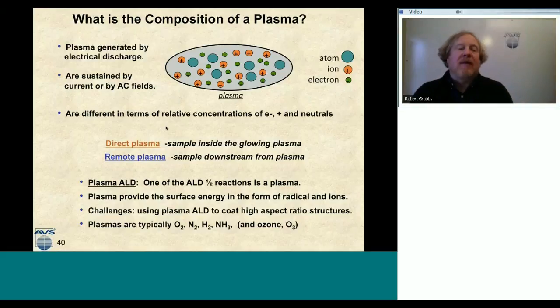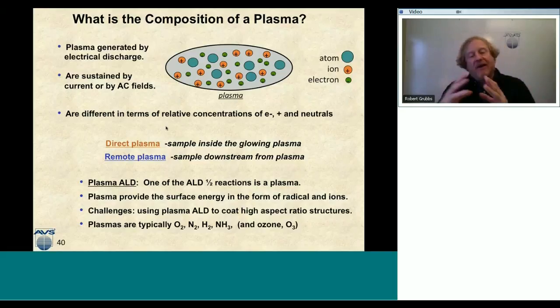So remote plasmas are typically lower in pressure due to increasing the mean free path, so that I can deliver or transport some of these radicals and neutrals down to my surface. So these plasmas are reactive, and they provide the surface energy in the form of radicals and ions to produce these chemistries.